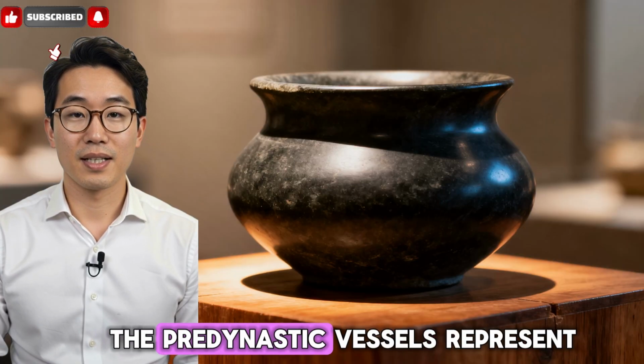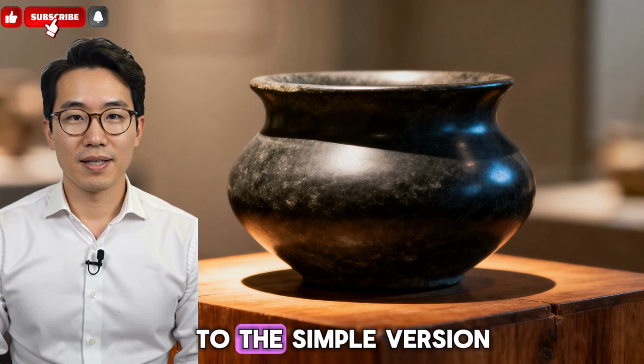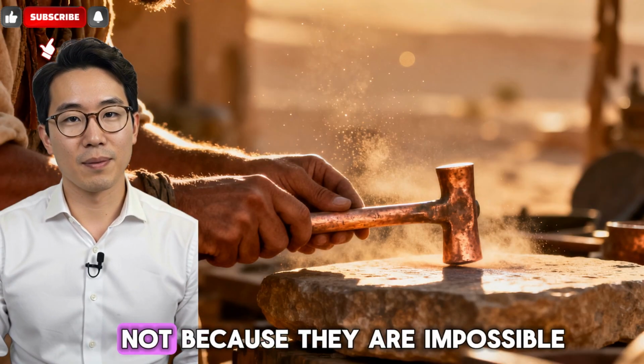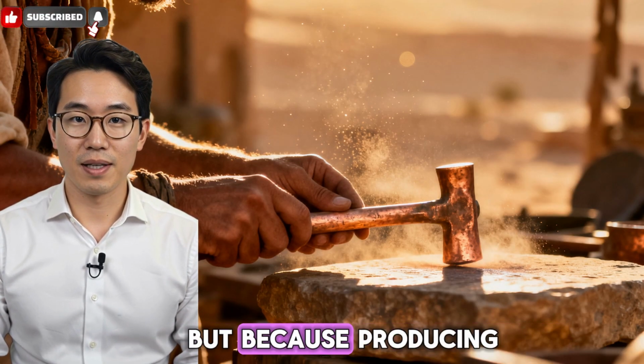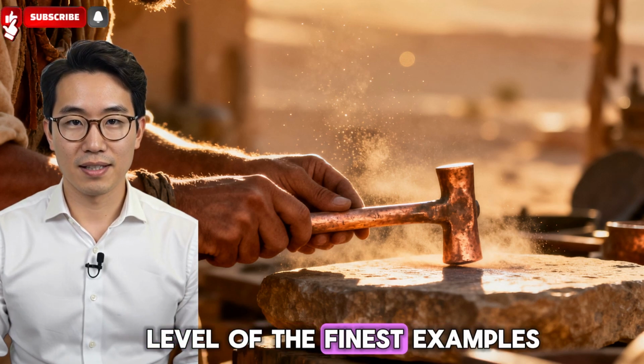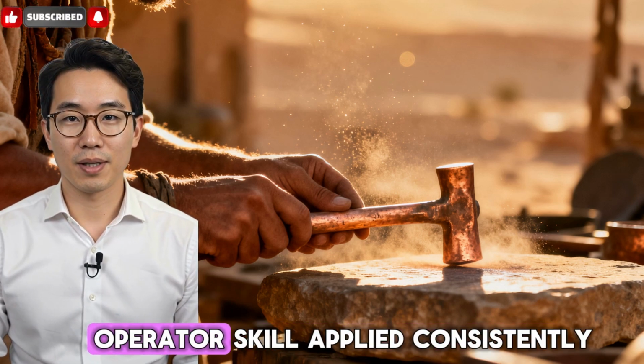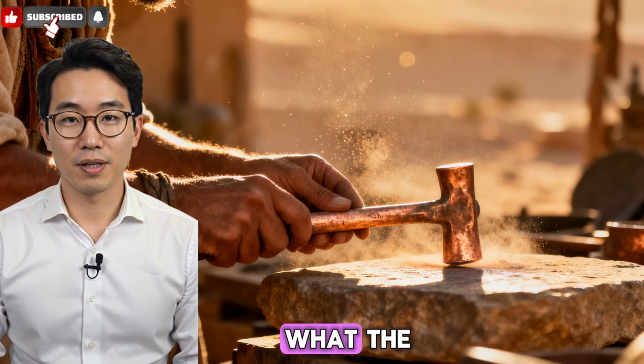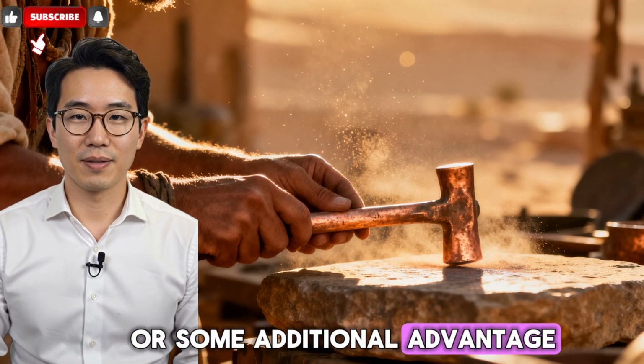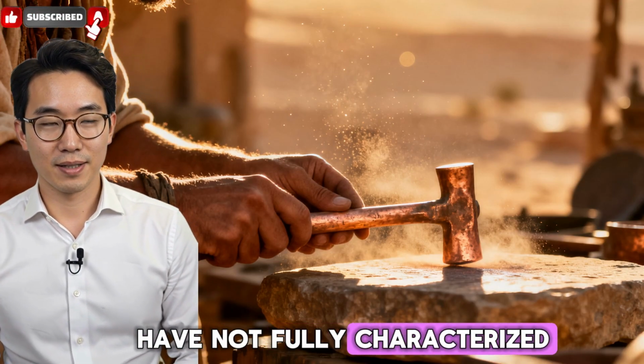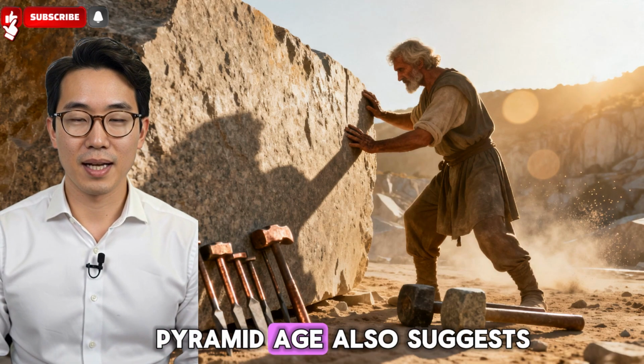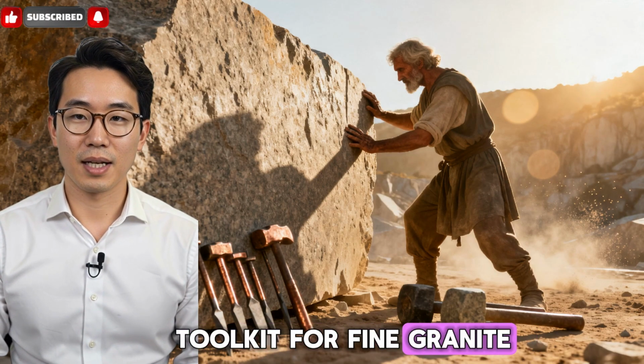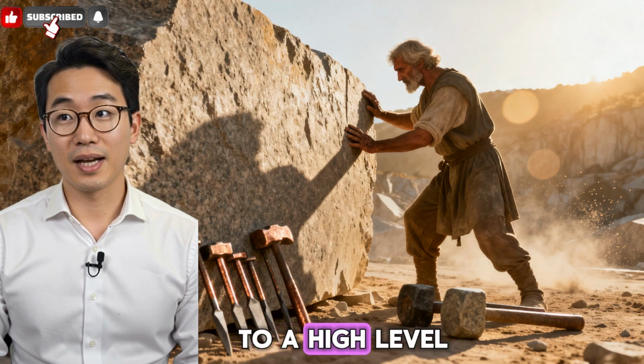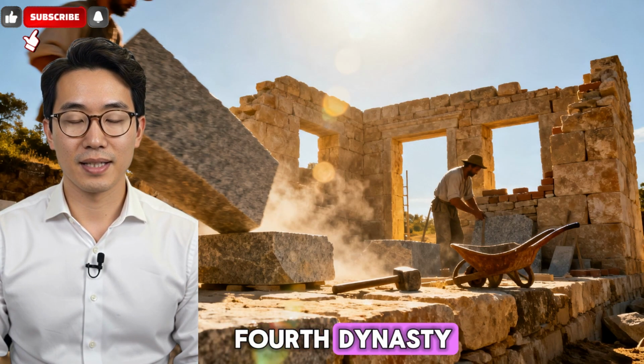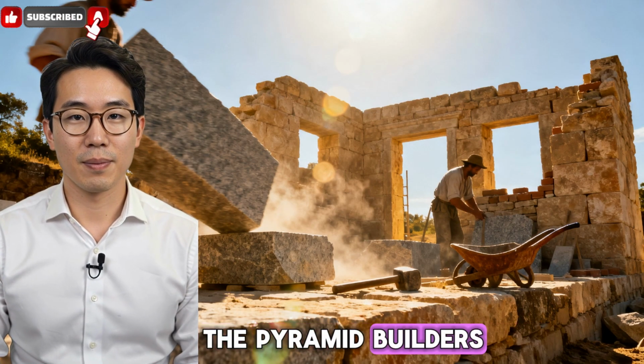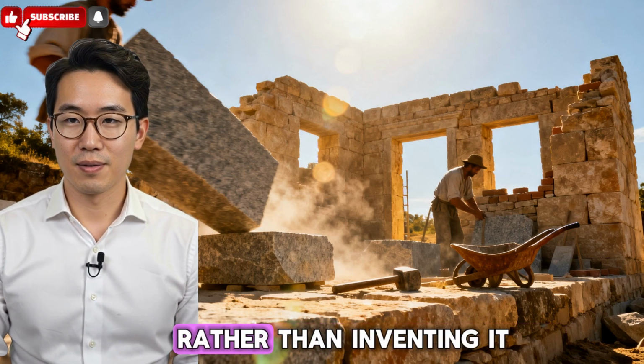The pre-dynastic vessels represent the earliest challenge to the simple version of the copper plus sand narrative, not because they are impossible with that mechanism, but because producing them at the quality level of the finest examples requires either extraordinary operator skill applied consistently at the limits of what the mechanism can achieve, or some additional advantage in the process that we have not fully characterized. The existence of these vessels before the Pyramid Age also suggests that the toolkit for fine granite working was already mature, already pushed to a high level of refinement, before the Great Fourth Dynasty construction program began. The pyramid builders inherited an already developed craft tradition rather than inventing it.